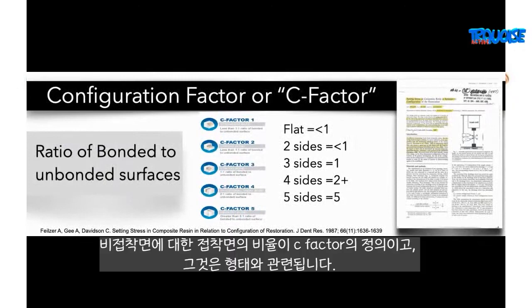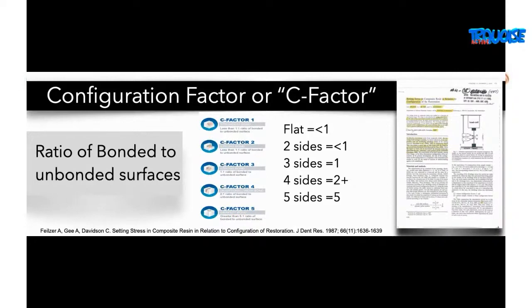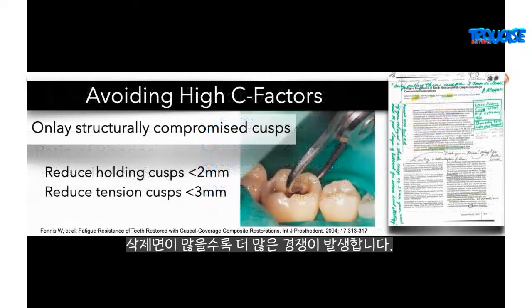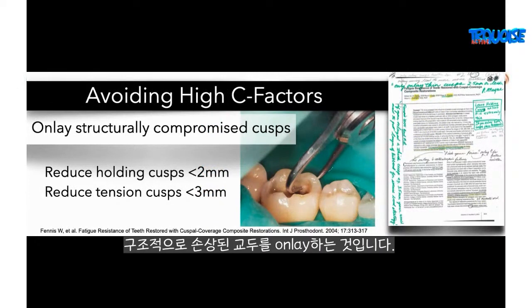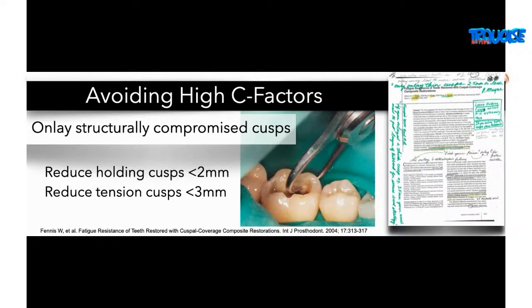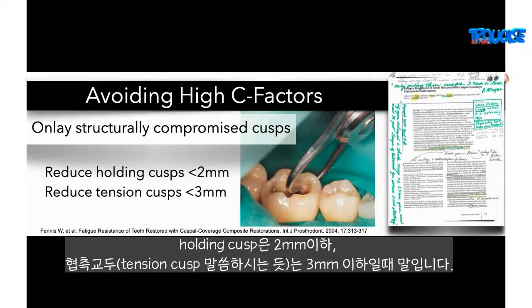So the ratio of bonded to unbonded surfaces is the definition of C-factor. It's the configuration. And so the more sides of the preparation, the more competition there is when composites start shrinking. One way to avoid or reduce high C-factor is to onlay structurally compromised cusps, that you would say are less than 2 millimeters for holding cusps and less than 3 millimeters for tension cusps.